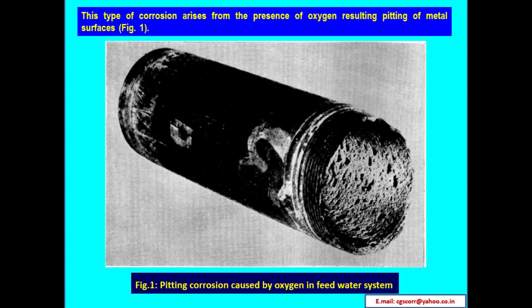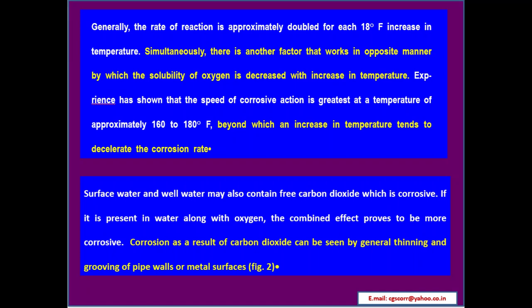Figure 1. Pitting corrosion caused by oxygen in feed water system. This type of corrosion arises from the presence of oxygen, resulting in pitting of metal surfaces. You can see pits, even see-through pits, holes in the piping system. Generally, the rate of reaction is approximately doubled for each 18 degree Fahrenheit increase in temperature.